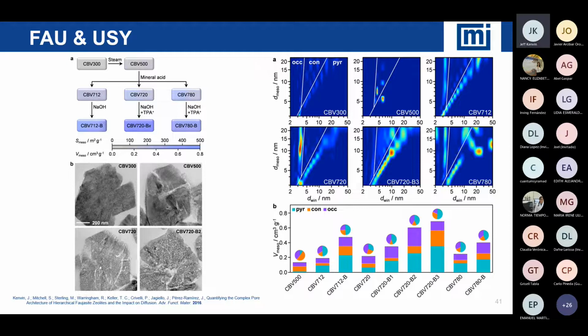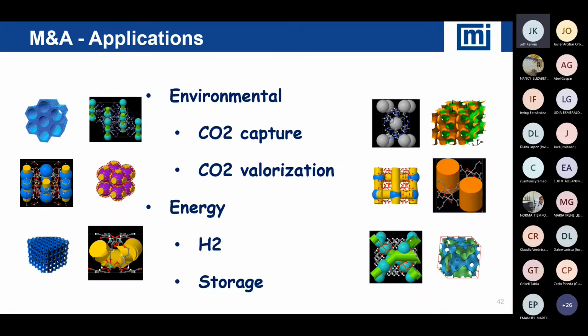We've done similar types of studies with faujasite. So again, commercially, the most significant material, catalytic material that's used globally, and we see the same type of behavior, that by using various forms of treatment, you can create different types of porosity in the materials. What's very nice about this is when we look at images in the lower left, the images agree quite nicely with what we're now modeling and calculating for pore size distributions.